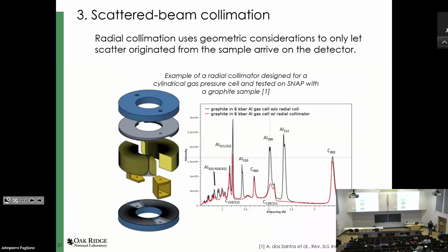We of course also play with radial collimation. So this is collimation of the scattered beam, where you can use geometric constraints to select that only the scatter from your sample arrives at the detector and not from the cell. So here's a typical radial collimator, or for X-ray experts, this is akin to Soller slits, for a gas pressure cell. So this is a cylindrical pressure cell, which works very well on the SNAP beam line. So here you see the aluminum peak. This is the cell peak, that once you apply the collimator, it's essentially removed. So these things, of course, are very critical also to reduce unwanted scatter and ensure you only see the sample's signal.